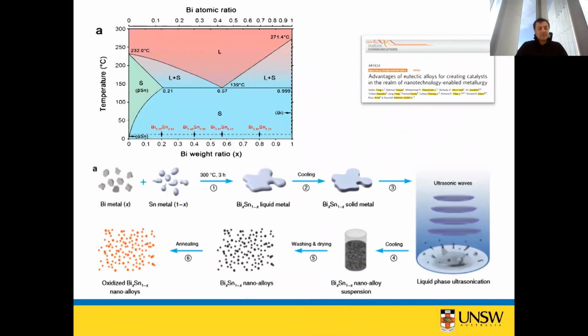Phase separation, this is the last part of this topic. Basically, classical phase separation is like you put two metals together and then at high temperature you melt them. They mix, entropy is high, so elementally they are mixed, but when you cool them down, they separate themselves into crystals, phase-separated crystals. Here, bismuth and tin. Bismuth melting point is 271, tin is 232. But they have a eutectic alloy with a much lower melting point temperature of 139 when bismuth concentration is 57% of the total weight.